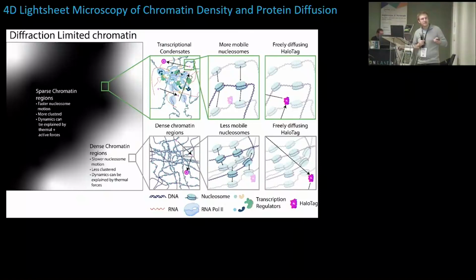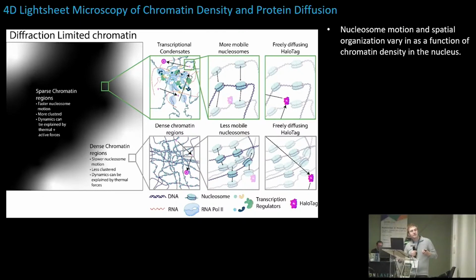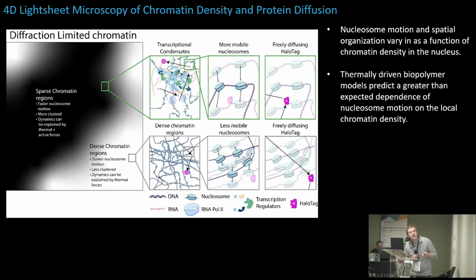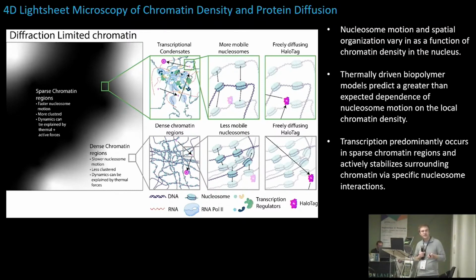So I think I'll skip over some of the overall summary of this. In sparse regions, we see faster nucleosome motion, more clustered nucleosomes, and dynamics that can be explained by thermal and active forces. And in these dense chromatin regions, we see slower nucleosome motion, more randomly packed nucleosomes, and dynamics that can be largely explained by thermally driven polymer fluctuations. Nucleosome motion and spatial organization vary as a function of chromatin density in the nucleus. Polymer models predict greater than expected dependence of nucleosome motion on the local chromatin density, and transcription predominantly occurs in these sparse regions. And our data support a model where these transcription condensates may locally stabilize chromatin into these active compartments over time.